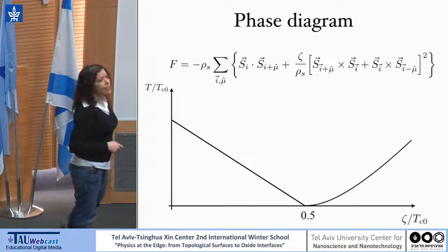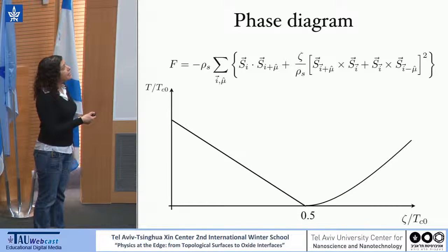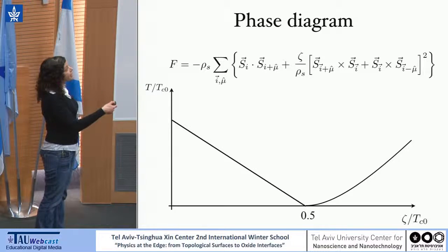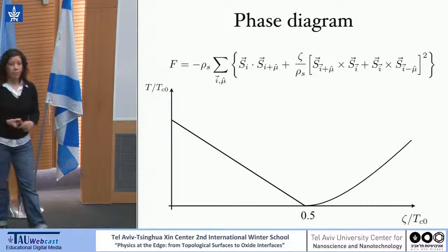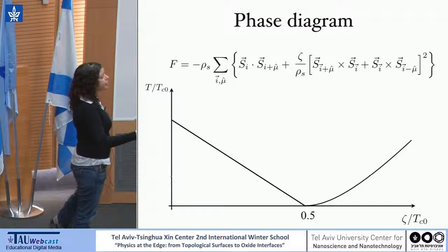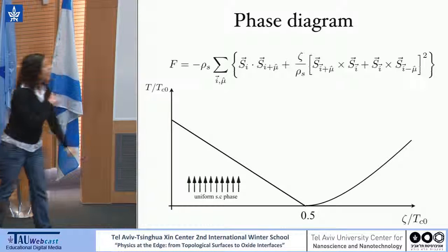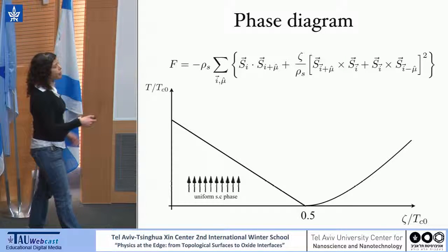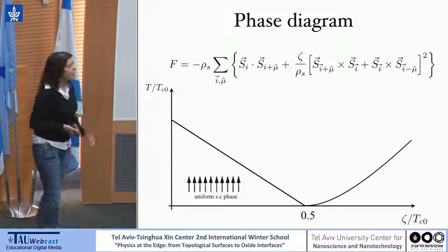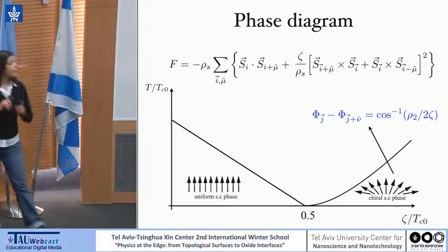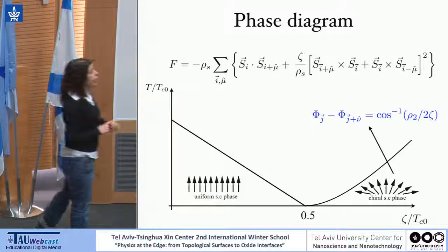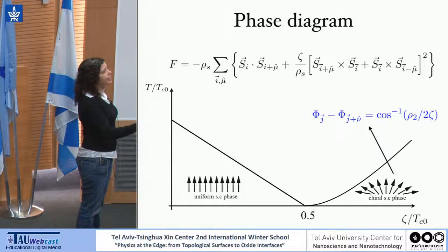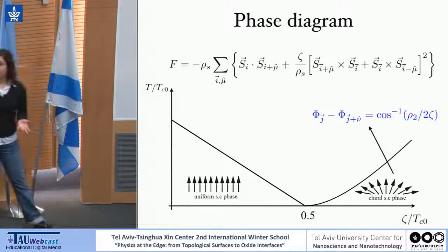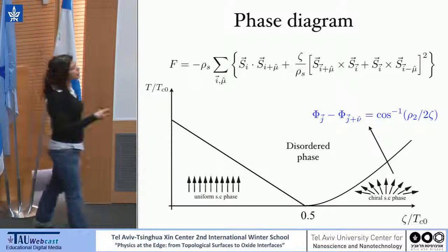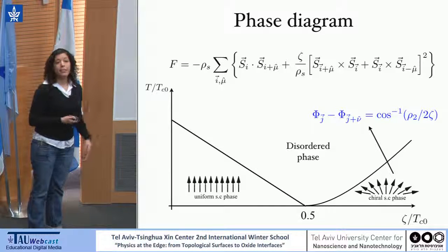And if we are looking at the phase diagram of such a system, we will see that initially, because of this competition between the two terms, we will get suppression in the phase stiffness of the system. However, above some critical value, we will have a transition into a new phase. And the difference between the phases is that in the beginning we have a uniform phase with suppressed phase stiffness that turns into just a chiral superconductor or helical superconducting phase where the gradient of the phase will acquire some finite value. And in between, we just have the regular disordered superconducting phase.